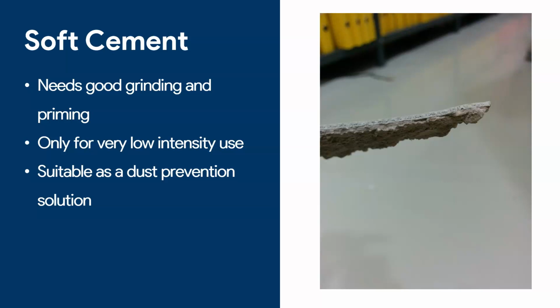Here's an example of this picture. You can see how the cement underneath has cracked and the epoxy kind of took the cement with it. So make sure that you do not use this. You can only apply epoxy on soft cement if it's a really low intensity use of the floor. If you plan on using the floor for anything heavier, you want to tear out the cement and put in a proper leveled concrete instead.